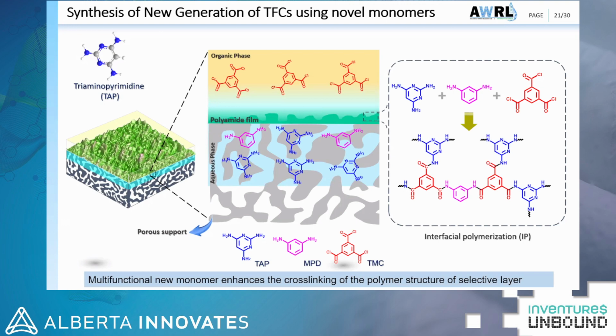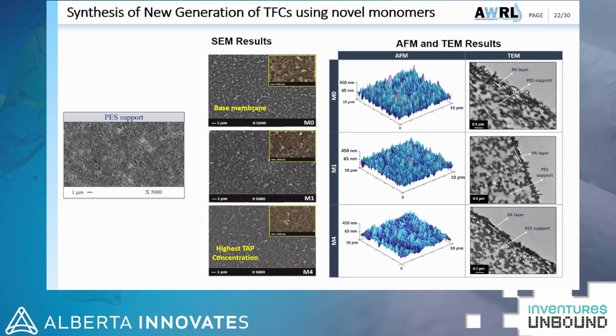The SEM characterization showed that the typical ridge and valley structure for all membranes was formed. But for the case of the modified membrane with the new monomer, the size of these ridges and valleys decreased. AFM results in the middle also confirmed that the roughness decreased by adding that new monomer to the mixture. And the TEM cross-sectional image also showed formation of a thinner membrane, which could potentially increase the flux significantly.